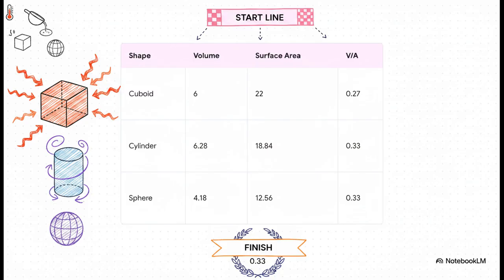Check out these three shapes: a cuboid, a cylinder, and a sphere. If you compare shapes that have relatively similar volumes, just look at how wildly the surface areas differ. The cuboid has a massive surface area of 22, meaning it bleeds off its heat incredibly fast. But the cylinder and the sphere? Their surface areas are much lower relative to their volume, giving them a higher volume-to-area ratio of 0.33. They are the clear, undeniable winners when it comes to retaining heat.